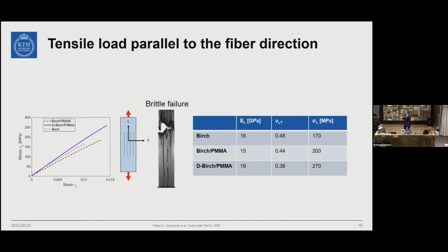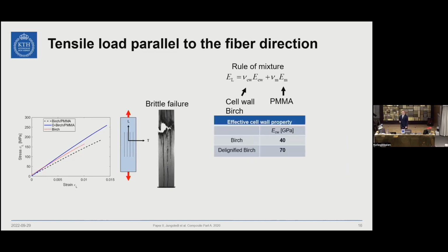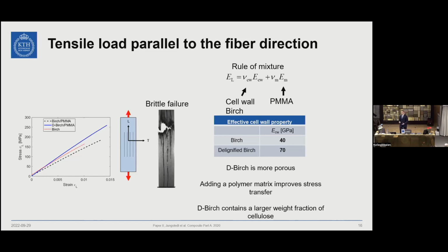What we can see by doing the delignification, we have an interesting reinforcement effect. We have a better elastic modulus and a better strength of this material. We can look at this reinforcement effect by using rule of mixture. And then we can see that actually the reinforcement becomes much higher for the delignified birch than compared to native birch. So the reinforcement effect is huge, which in some sense could be a bit non-intuitive, since we're increasing the porosity by doing the delignification.